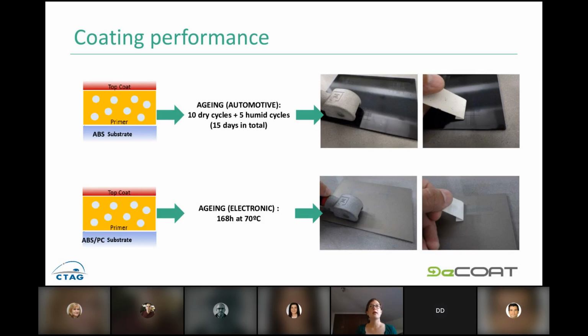We also assess the coating performances because as we modify the coating with these triggers, it means that we are at risk that the debonding process starts before the end of life due to the environment, the aging. So we want to be sure that the coating is stable, easily removed, but only with the proper triggers and the proper temperature, not during the life of the part.